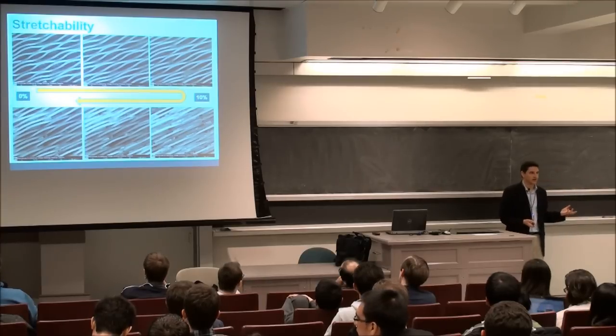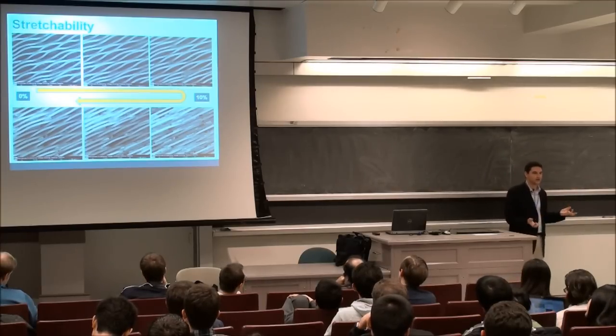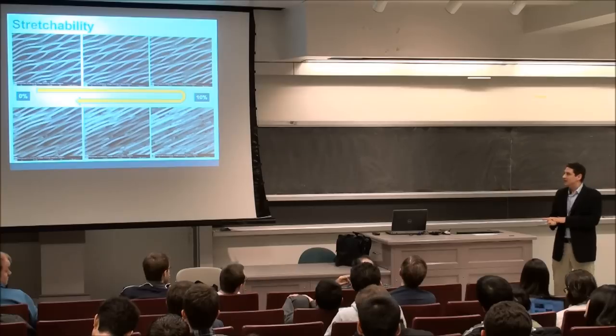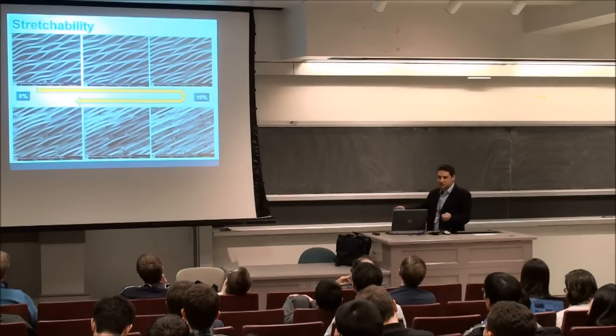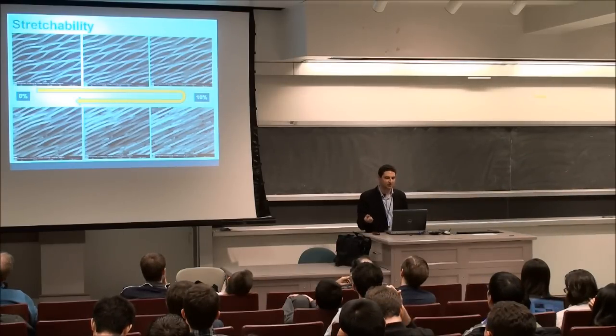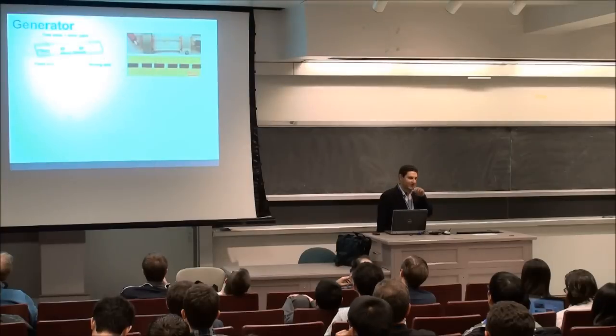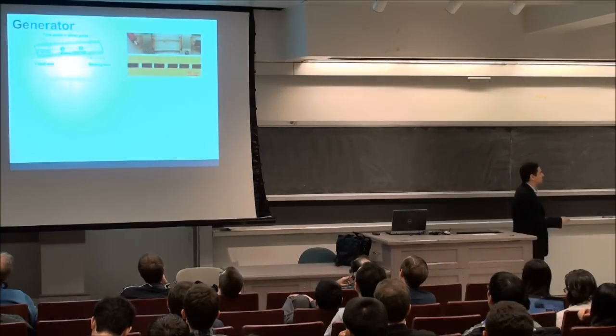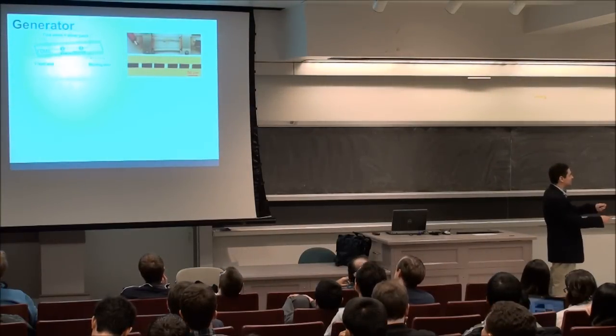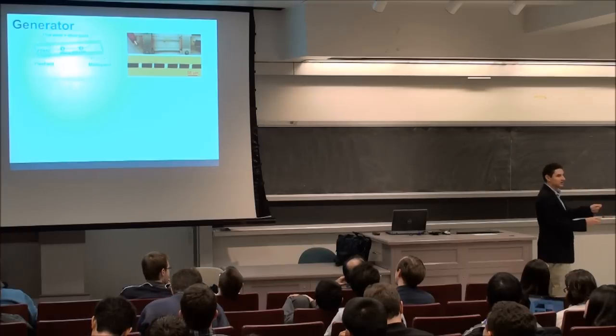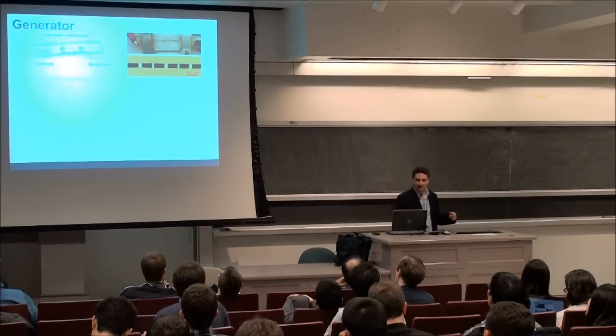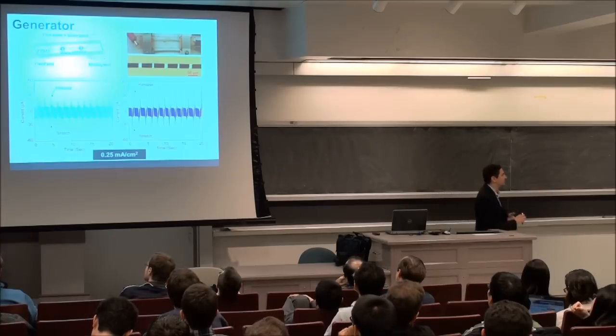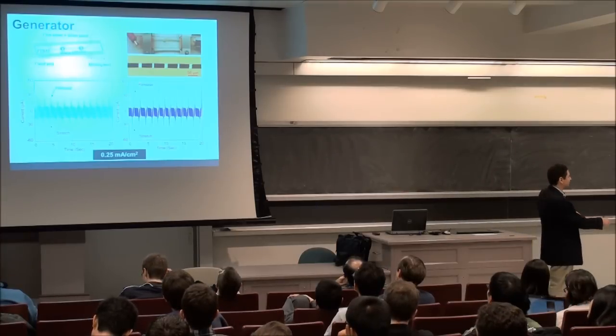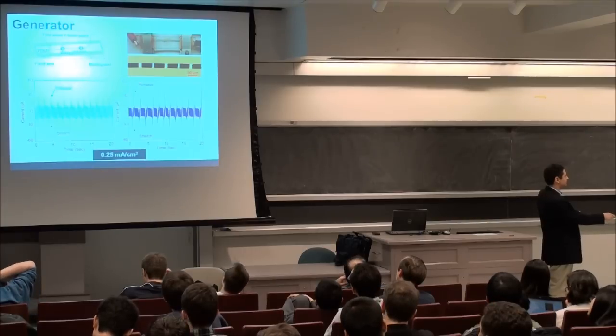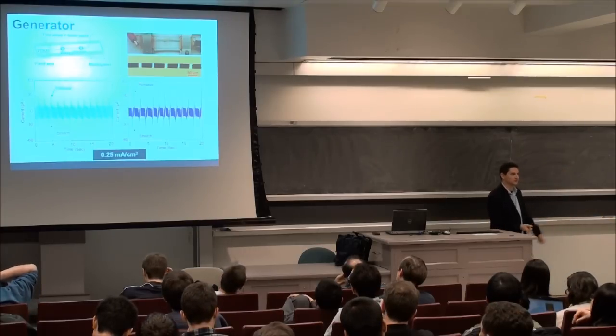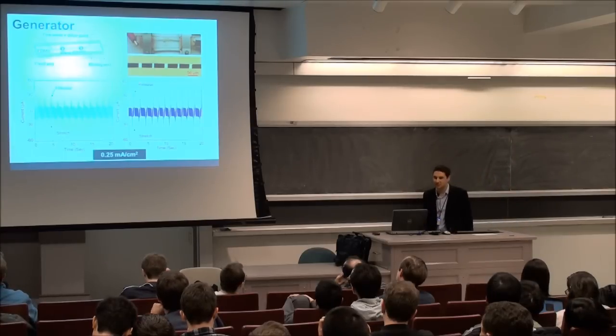And so in our case, this is interesting because, again, no stretchable piezoelectric has ever been made. And also because as you stretch it out, you're actually deforming the crystal. So you should be able to generate power that way. And in fact, we did. If you put silver paint at the end here and you stretch this thing out, here's our buckled ribbons here, you actually will generate little spikes of power as you do it. And just to prove that this is from the ribbons and not from the electrodes, we can actually do 5 ribbons here or 10 ribbons here. You can see you get double the current as you add more ribbons to the system. So you can generate power in this kind of stretching mode.